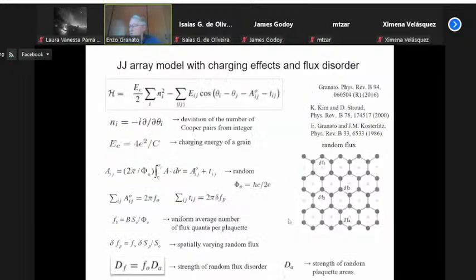And the model we consider to describe the system is again a model with a charging energy, but now we allow the vector potential to have a contribution which comes from disorder. So we consider a model in which the grains are still defined on a honeycomb lattice, but the area of each plaquette gives rise to a different flux. So there's a random flux from one plaquette to the other. And that's a particular way of defining the model that is convenient, especially for numerical work.